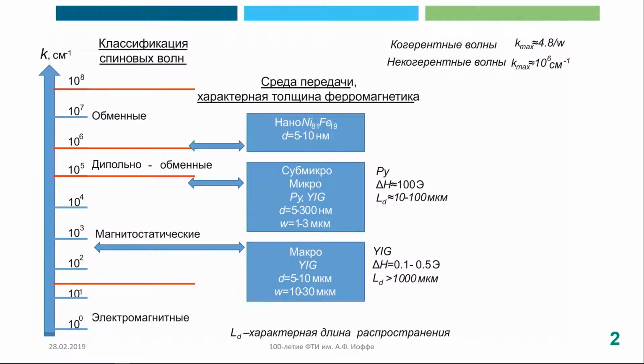And different materials. The best material, as I said, is yttrium iron garnet, because losses are very small in this material. However, you also can use permalloy materials, nickel iron alloys, and for some ways, for nanostructures, losses for propagating spin waves are very small.